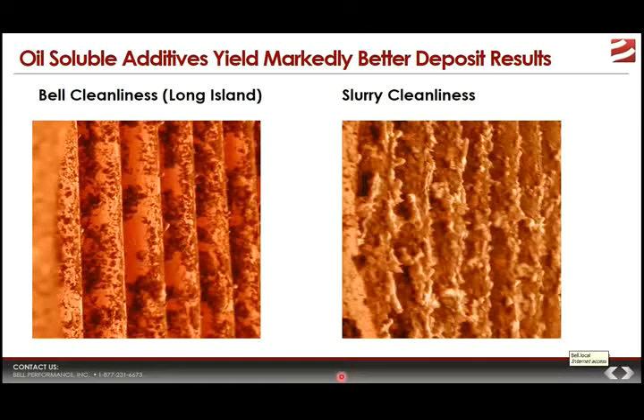So in the end, with these marked differences between magnesium oxide slurries, how they work, and soluble magnesium and how it works, the proof is in the pudding. And here, the proof is a customer in Long Island that for years used magnesium oxide, MagOx. They had their own dedicated holding tank. They pumped it into their fuel oil, and this is what their tubes looked like. Not very clean. They were switched over to the ATX formulation, typically 1020 is what they used, which has the oil-soluble magnesium, and this is what those tubes looked like after a period of time.